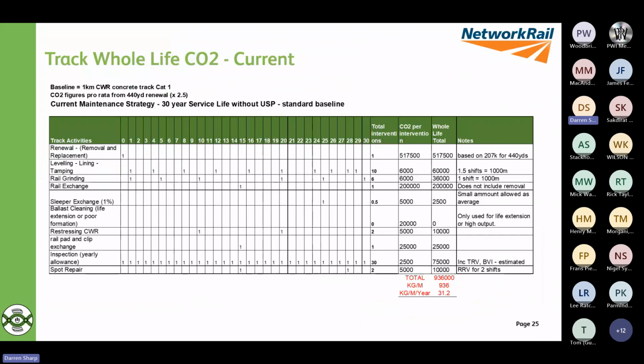If you put that onto a table, this is a baseline with 1 kilometre CWR concrete track, Cat 1. So it's a 440. It's based on a 440 yard renewal pro rata, so it's 2.5. So it's creating a 1 kilometre track, using our current maintenance strategy, 30-year service life, and that's without an undersleeper pad. So a standard baseline.